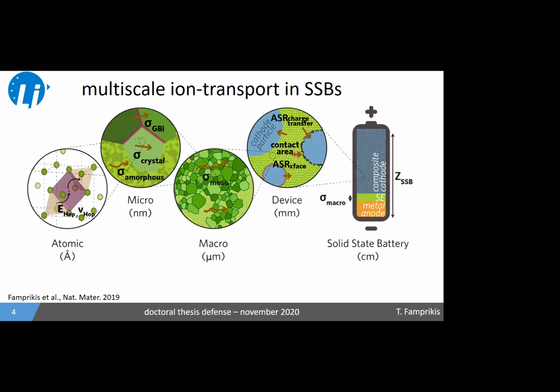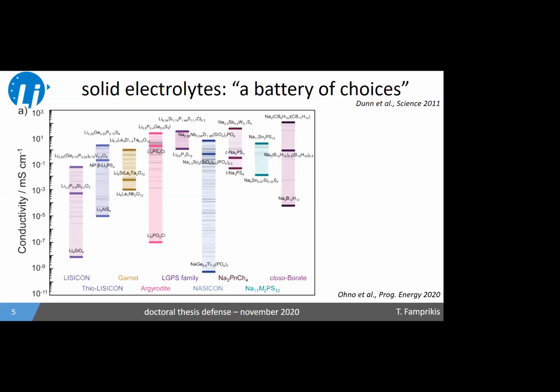Nevertheless, the last 10-15 years of research have allowed us to discover and study in detail a lot of solid electrolyte families with respect to their high ionic conductivity, which is what I'm plotting here from the recent review. Typically, we talk about families as a function of their composition, their chemistry, and their crystal structure. So you see different families shown here, and what is important to highlight is that we're now at a point where we know of a few different families of materials that can reach the ionic conductivity of liquid electrolytes and can, as such, be envisioned as battery electrolytes.